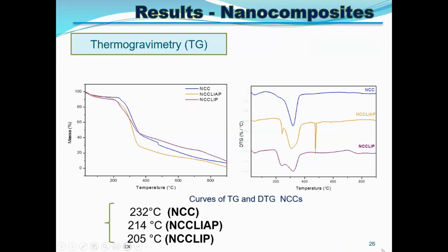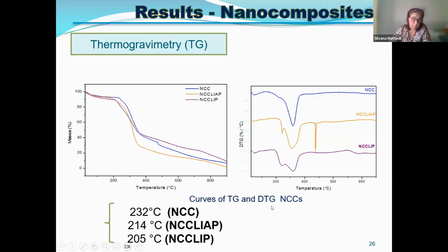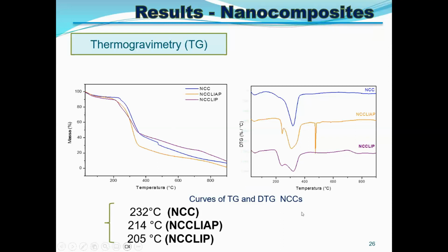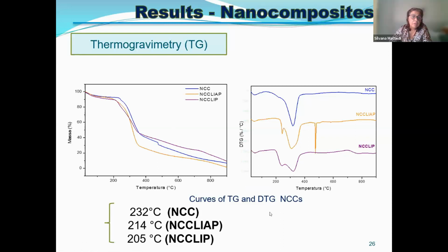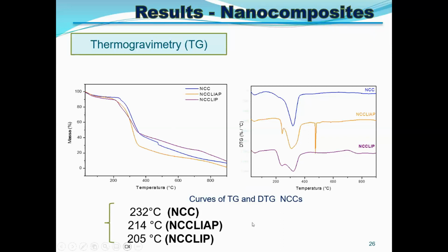The thermogravimetric analysis shows that the materials have similar behavior. The protic one has a lower degradation temperature, and the one from sulfuric acid has a higher degradation temperature.